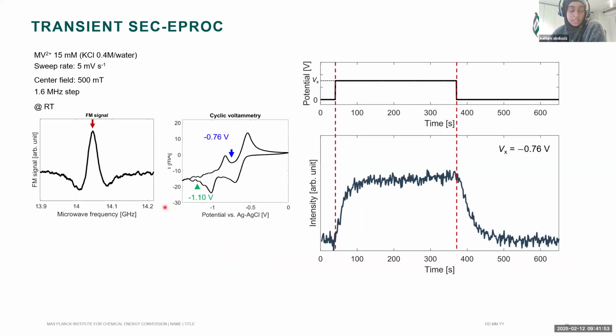And the final type of experiment that he did in his system was a transient electrochemical experiment, where he sits at a maximum intensity and then applies a potential. So in this case, he applied it where this blue arrow is, and then measured the intensity of this signal as a result of the potential applied. So with this, you can really see the increase in intensity, the leveling out, and then also the decrease of the intensity. So if you want to look at systems where species are being generated very fast or in very low concentrations, this transient spectroelectrochemical EPR would be very nice. At this point, he went down to 1 second per point. However, with rapid scan, he can go down to milliseconds.